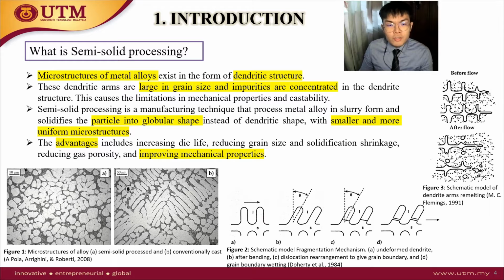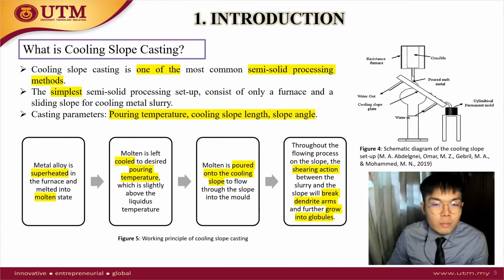Semi-solid processing is a manufacturing technique that can process metal alloy in slurry form and solidifies the particle into globular shape instead of dendritic shape, with smaller and uniform microstructure. The advantages include increasing die life, reducing grain size and solidification shrinkage, reducing gas porosity, and most importantly, improving mechanical properties. Cooling slope casting is one of the most popular semi-solid processing methods. It is the simplest semi-solid processing setup, which consists of only a furnace and a sliding slope for cooling metal slurry. Its casting parameters include pouring temperature, cooling slope length, and slope angle.